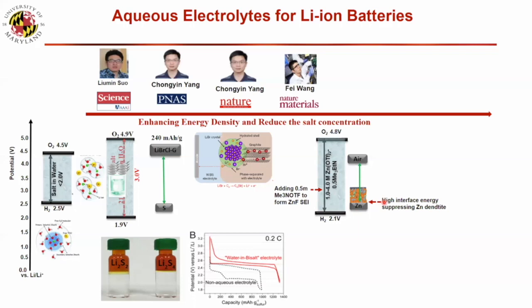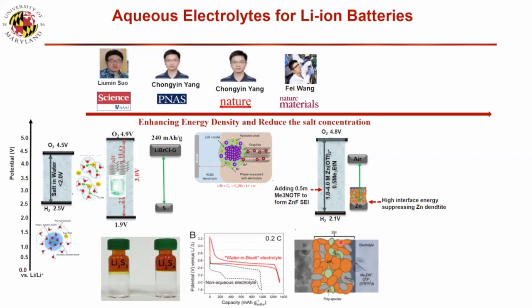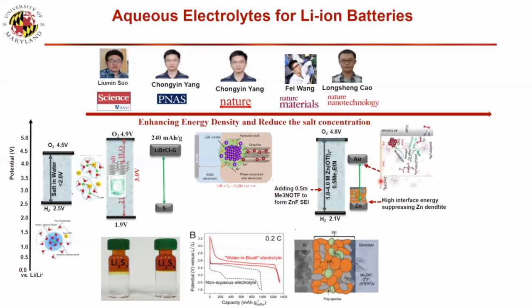And the same principle. We check all the ceramics, and among zinc fluoride and zinc carbonate, zinc fluoride has the highest interface energy. Then we develop, on purpose, a zinc carbonate and zinc fluoride SEI cover on the surface. This is formed in situ. And also,